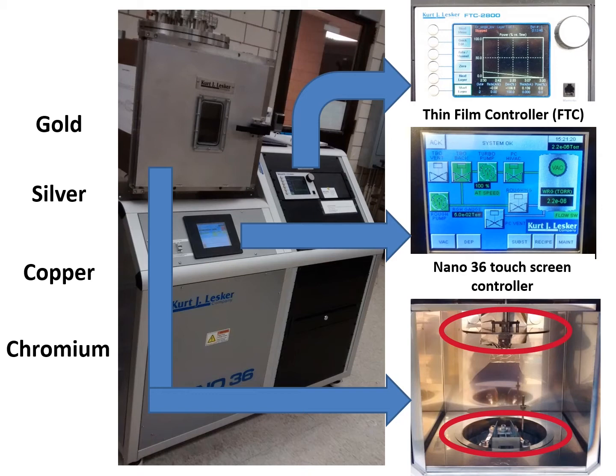Evaporation is controlled via a quartz crystal sensor in conjunction with a thin film controller. It ensures automatic control of the film thickness. Using the FTC, the films and the processes can be selected and edited. This display shows the process selected, the film used, and the deposition process flow. It can also display different graphs during deposition, which include the power versus time, the deposition rate versus time, and the deposition rate deviation versus time.